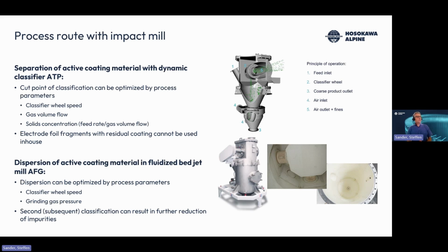And as I've shown you, you can further process this material for obtaining the needed particle size distribution here. And you can see the outside of a jet mill here, but it's quite common to protect the inner surfaces of these mills with all kinds of ceramics in order to avoid contamination by metals coming from the mill itself by abrasion.